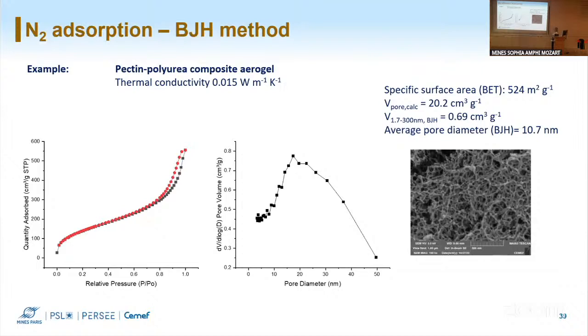I'm confident. First of all, this is the value given directly from the nitrogen adsorption, given from the machine itself. It's not calculated by me. Then we can calculate the pore volume from the skeletal and bulk density. Which means you have a lot of macropores that you don't see. We don't suppose that we have micropores. We suppose that probably the method is not suitable for our materials. So I don't understand the discrepancy. I'm sorry to insist, but 20.2 versus 0.69.